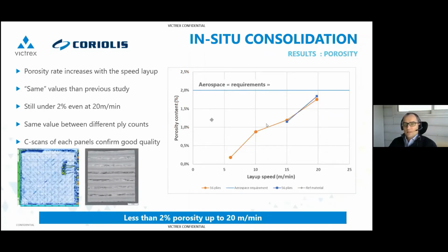And you will see that's also the trend for the rest of the criteria. So this one was about the porosity inside the laminate. For the aerospace requirements, the state of the art is that you want to be below 2%. That's the threshold. So we've been able to stay below this threshold up to 20 meters per minute, which was also pretty positive.